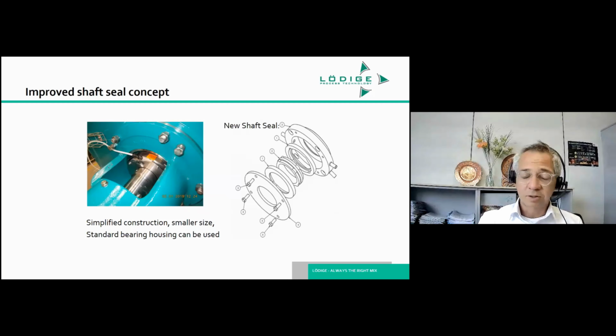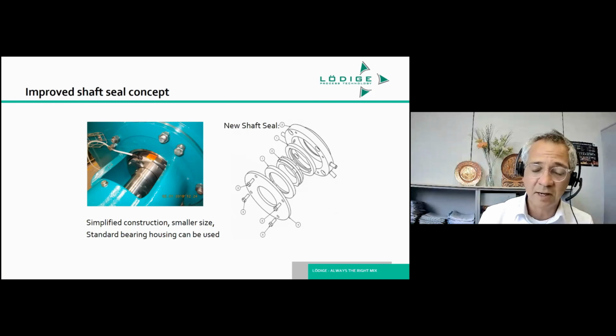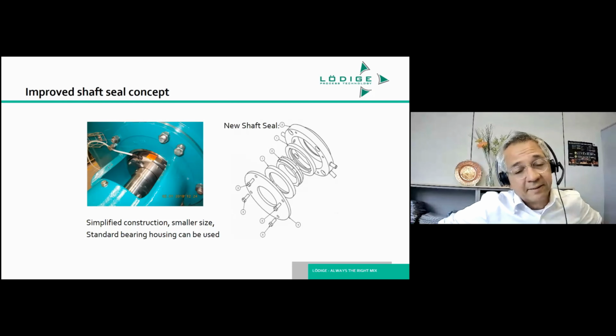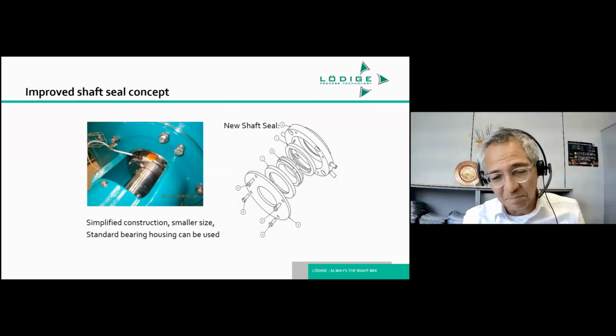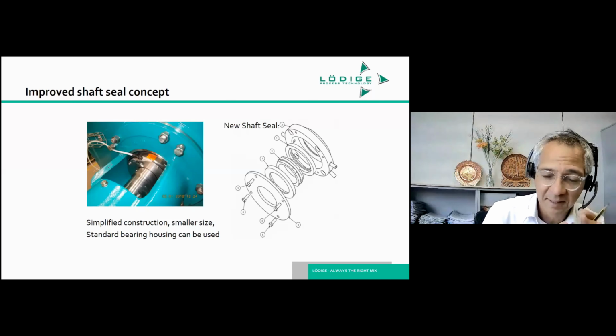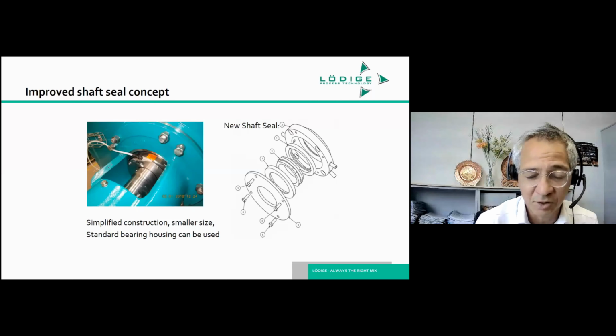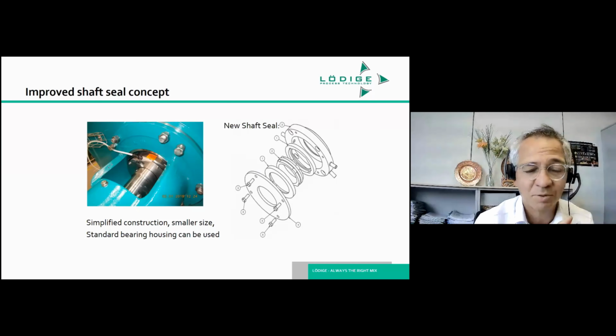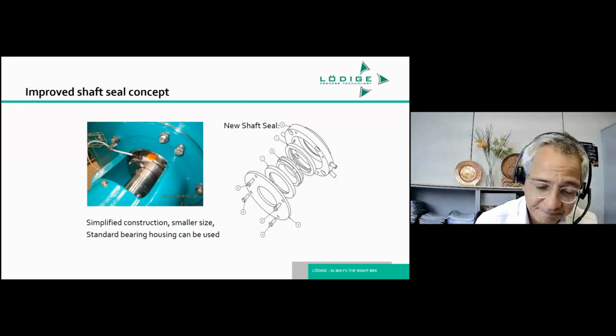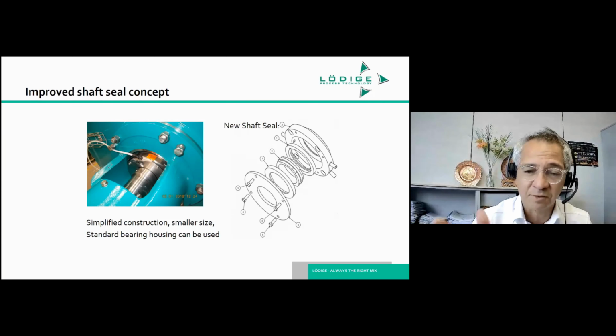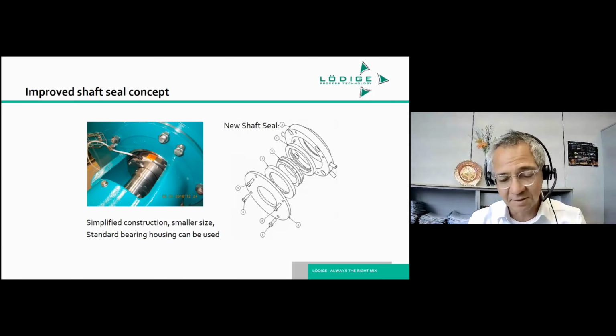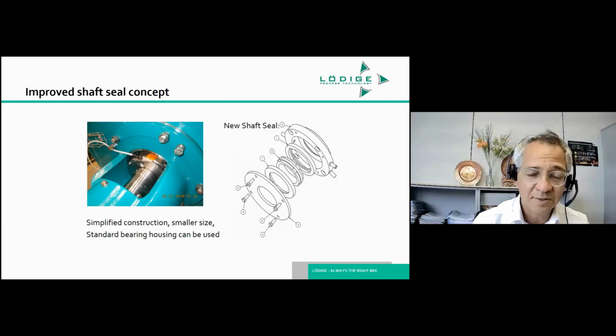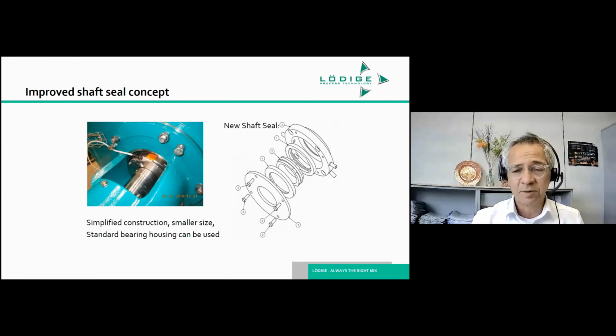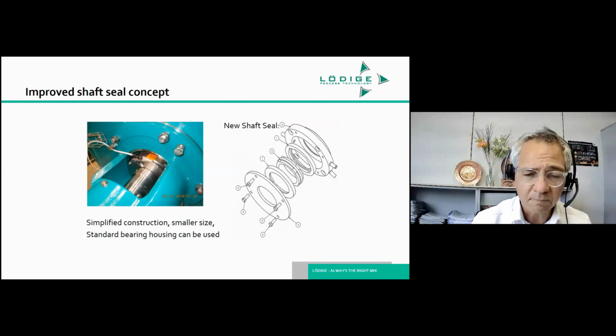But again, the more you look, the more you see details and the more you see areas where potential contamination can occur. And you can see that mixing not only involves the mixing process, but it also involves side issues which you have to deal with. And yeah, the focus today is on contamination prevention. And then customers were looking at, hey, we have here a seal. It's air purged. It's good. Air purging keeps material inside the mixer. There's no escape of toxic material via the shaft seals and amassing in a heap next to the mixer. But what about the air going into it? How is it treated? Where does it come from?